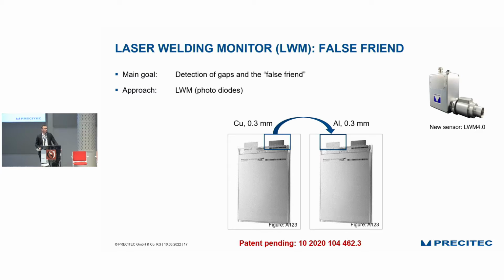So this is how this sensor works in general, and now let's go into one particular case of e-mobility where a customer wanted to see if you have a good weld for pouch cell welding, copper 0.3 millimeter, galvanically coated, to aluminum, and he wanted to see if there is a gap and if this gap is bridged or not. The wording we use here is false friend. It's an overlap weld, and by pure inspection with your eyes, you cannot see if it's a good weld or not. The question is, can we see it in the process emission? And the answer comes next.